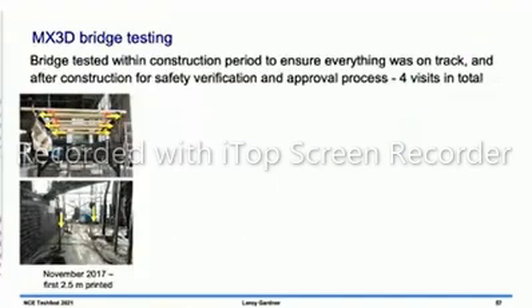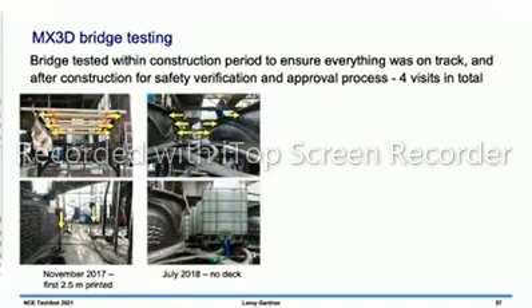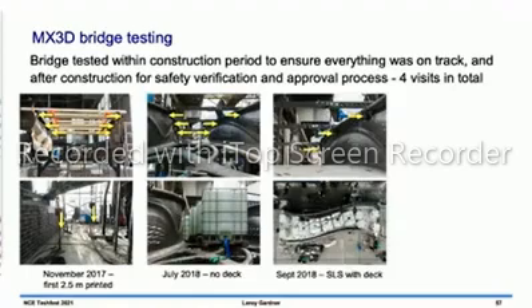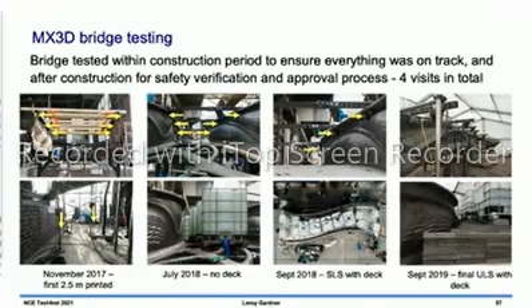All of that testing was to destruction, and then the final set of testing was on the bridge itself, and we didn't want this to be to destruction, but we did want to go up to the design loads that the bridge would be subjected to in practice. So we had 4 trips over to the Netherlands. First trip was in November 2017, when the first 2.5 meter length of the bridge had been built, and we did some preliminary tests. We then went back when the full bridge had been printed, but with no deck in place. And then in 2018, the deck was welded in place, and we did what we called the serviceability loading tests. So this was up to the serviceability design load of the bridge. And then the final set of tests, we went up to the ultimate limit state design load of the bridge. And with all of these tests, we were recording lots of information about how the bridge was behaving and comparing with some models that we'd made.